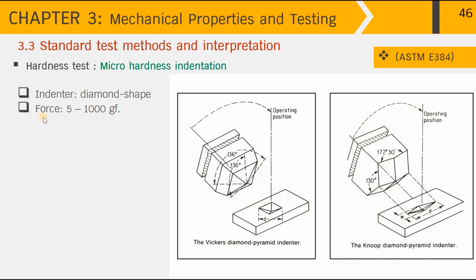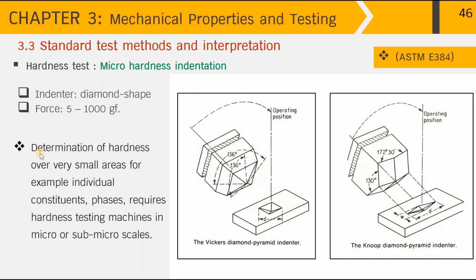indenter. And the force can range from 5 to 1000 gram force following ASTM E384. And with this small indenter size, we can determine hardness over very small areas, for example on individual constituent phases, that requires a hardness testing machine in the micro or sub-micro scales.